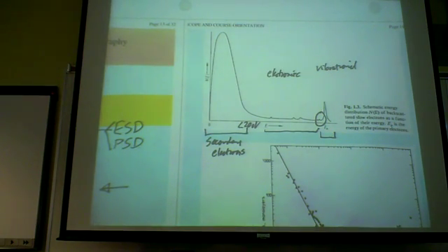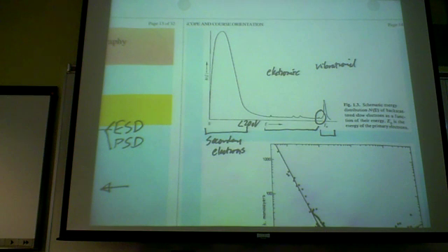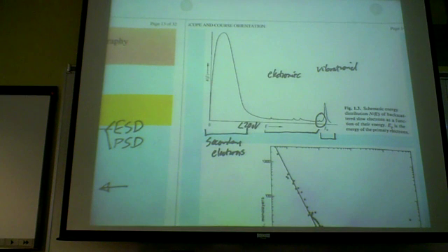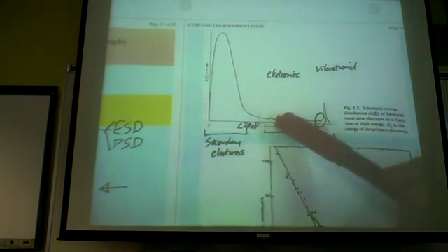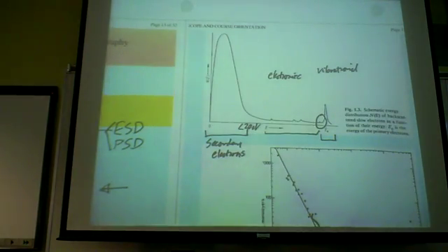They do not depend on the type of material that you have, whereas the location of these other peaks would depend on the material. So gold would have a different peak location compared to silver, for example. But if you look at gold and silver, the secondary electron peak is usually the same. They are featureless. They are just a drop of electrons emitting very close to the surface, within 2 to 10 nanometers, if you like, from your surface.